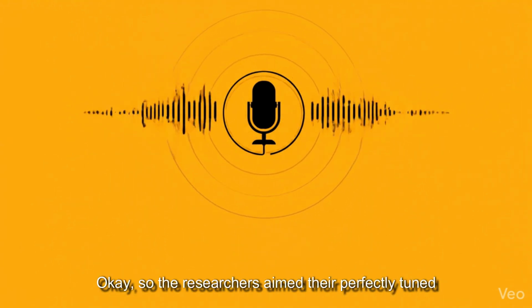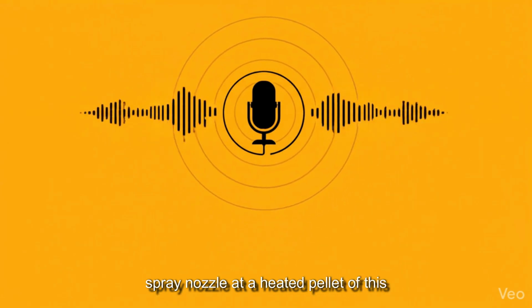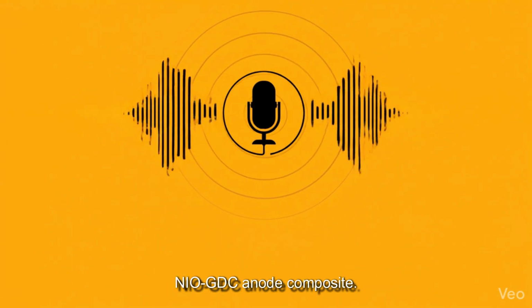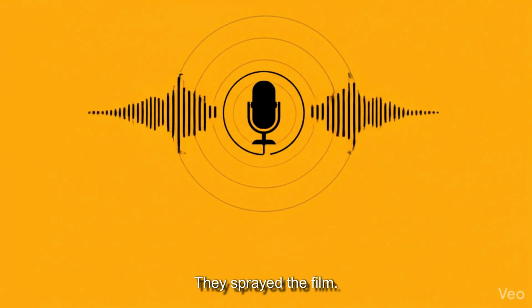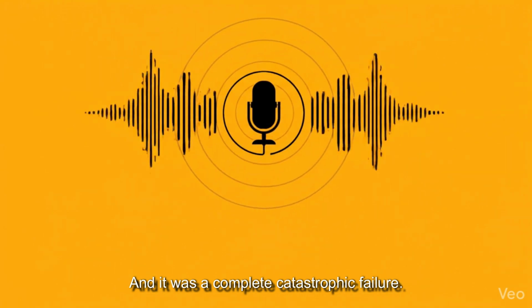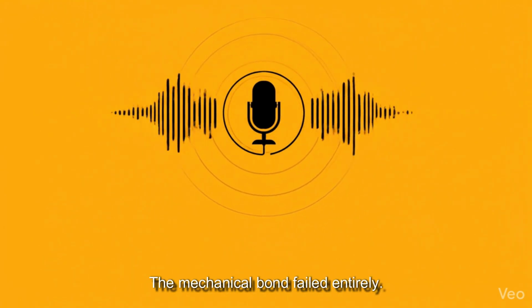Okay, so the researchers aimed their perfectly tuned spray nozzle at a heated pellet of this NiO-GDC anode composite. They sprayed the film. And it was a complete catastrophic failure. Oh no, what happened? The film wouldn't stick. Yeah. The mechanical bond failed entirely.